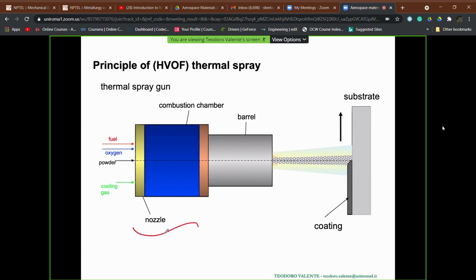In this case, also in the case of HVOF, we have a gun that, depending on the type of technology which is used, can be a little bit longer than the torch. This is the real name of the gun for the plasma spray technology. And it has a combustion chamber inside the gun, since the energy is given by combustion. So we need to use a fuel, and then the combustion, in order to achieve the highest possible temperature, is done by using not air but oxygen.